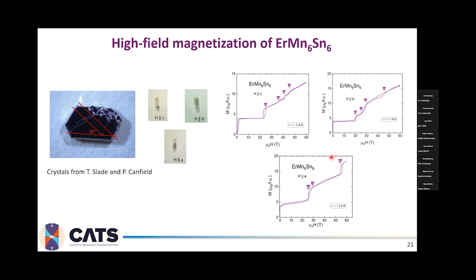So this is the A direction, which I just showed. The B direction shows many more transitions and also very small details. And the C direction again has the transition around 25 Tesla, followed by three little transitions. The interesting part over here is that none of these magnetization curves actually saturates up to 60 Tesla. They all stay unsaturated and pretty linear when we are close to our magnetic field limit.